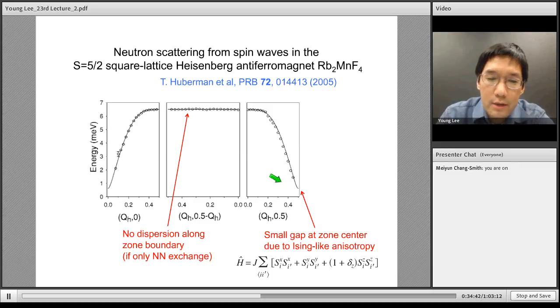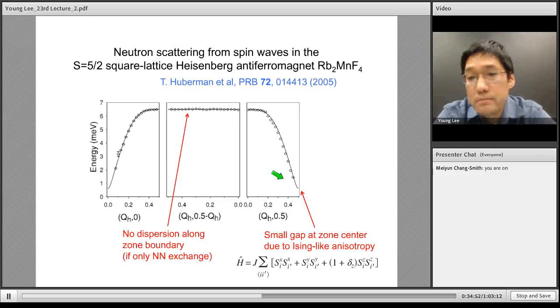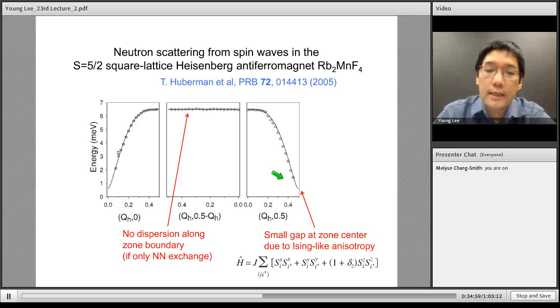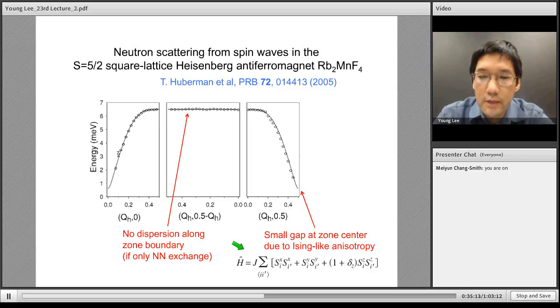I guess it's not really clear in their data, but there are other results with lower energy data points that show that there is a small gap at the zone center. This means that it's not just the perfect Heisenberg model, that there's some additional term in the Hamiltonian, such as a spin anisotropy. You can modify your Heisenberg Hamiltonian in the following way. If you just had these three terms with the same prefactors along the x, y, and z direction, that would be Heisenberg. But now you have some additional delta here for the z term. So you have an Ising-like anisotropy along the z direction in this magnet, and that will give rise to a small spin gap.